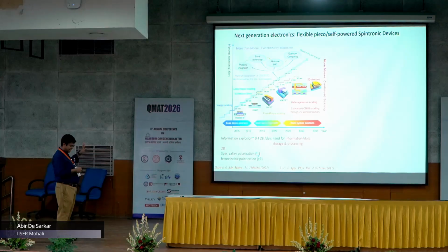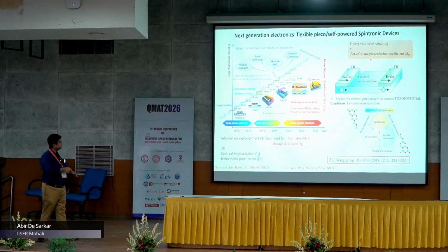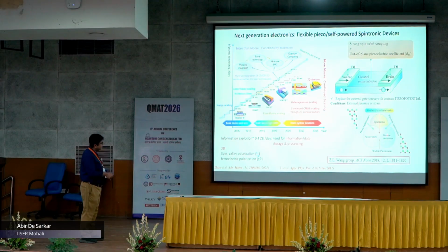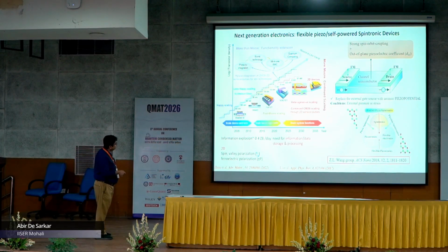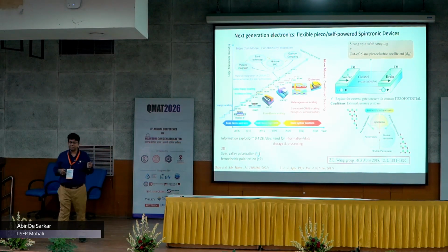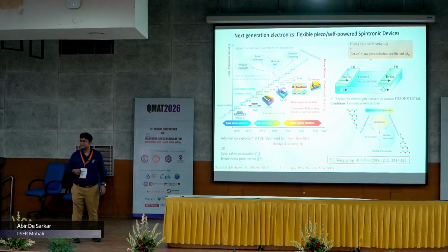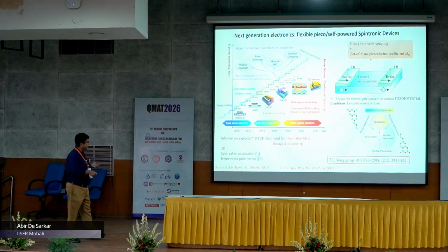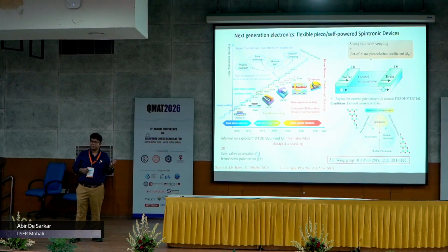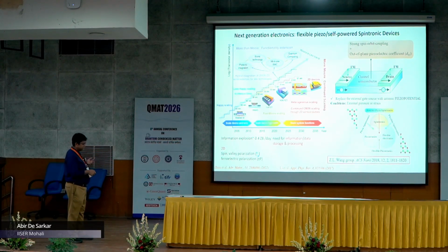If you reconcile these two aspects, the next generation channel semiconductor would demand a seamless merger of three properties. That is, the channel semiconductor needs to have a strong spin orbit coupling or a high Rashba constant, and a high out of plane piezoelectric coefficient, so that the external gate voltage source can be replaced by the intrinsic piezo potential under the application of external pressure or strain. Low dimensional materials or two-dimensional materials are by default flexible and stretchable. By default, they meet this criterion. So in summary, the next generation channel semiconductors need to be multifunctional. That is the motivation behind our working on multifunctional two-dimensional semiconductors.